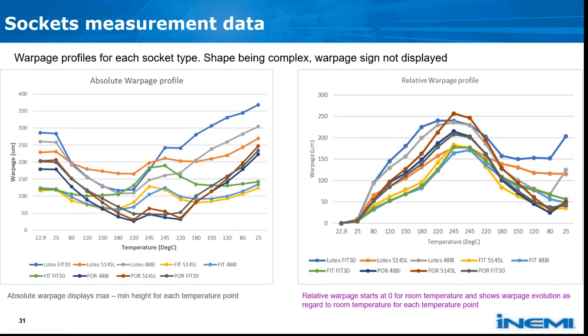If we check the relative warpage at the right graph, we can see that if we do not consider the initial shape, and we just consider the shape variation of each sample with regard to its initial shape, all the sockets are showing a warpage increase during the heating process and a decrease after a while in the cooling. Some samples are showing a very similar shape or low relative warpage, which means that when it comes back to room temperature, we recover more or less the initial shape. Although the blue one, lot 30, is showing some variation, some permanent change, I would say.